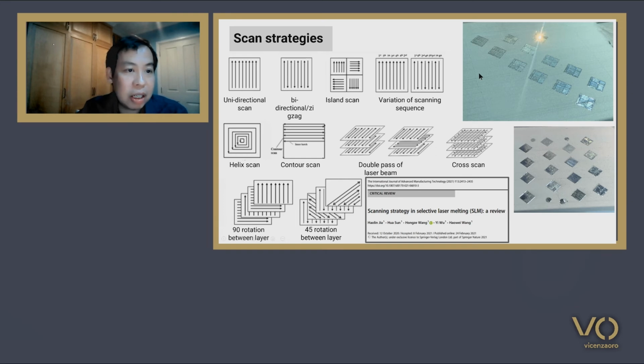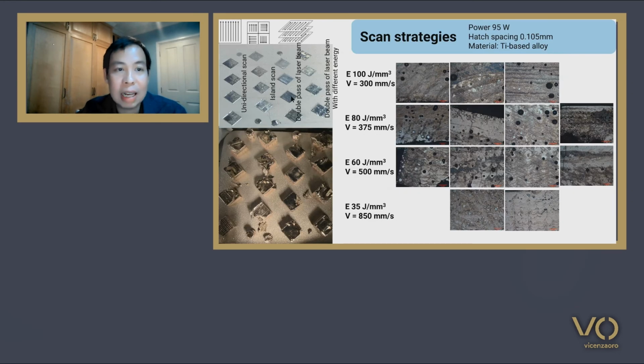With the scan strategies, I think we found the island scans to be working quite well, and also double pass of the laser beam as well. This also helps in the sense of the residual stress. But as you see, when the energy is too high, there are some holes, there's some pores, and when energy is low enough, there is a more dense sample. But you would see some of these dots down here are unmelted powder actually. So there's always the art to balance all of these scan strategies to work properly.